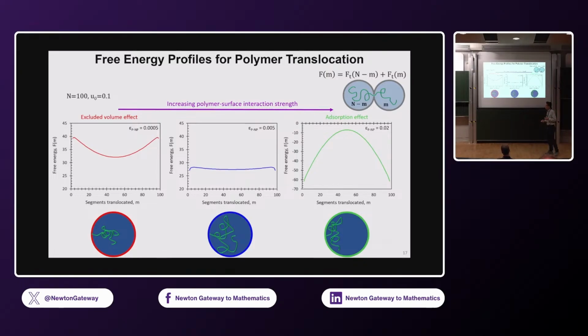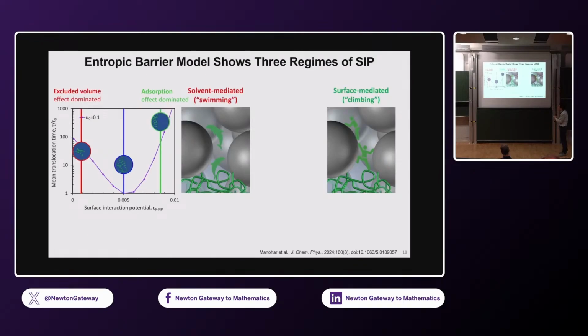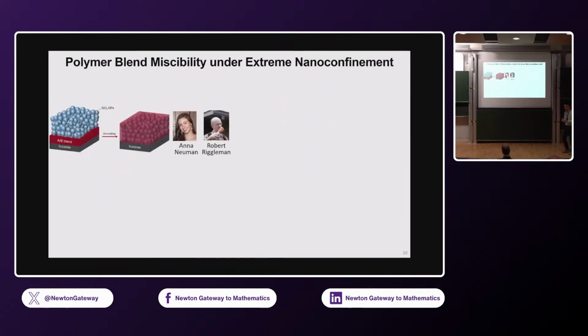Okay? So what is the net result of this? Net result of this is that when you have polymers that are not very sticky, you have some translocation time. And then when it becomes very sticky, again, it wants to stay in the first pore. So it takes a very long time for it to go into the second pore. So in the first regime, you have polymer that is swimming through the pores that are solvent filled. Whereas in the second case, the polymer now has to climb by sticking to the surface. Okay, and I had a very creative student. In between, what we have is what she calls the Little Mermaid regime, where you can either climb or swim. So you can take advantage of both of those mechanisms to undergo infiltration. And that's why we see this enhanced infiltration dynamics.